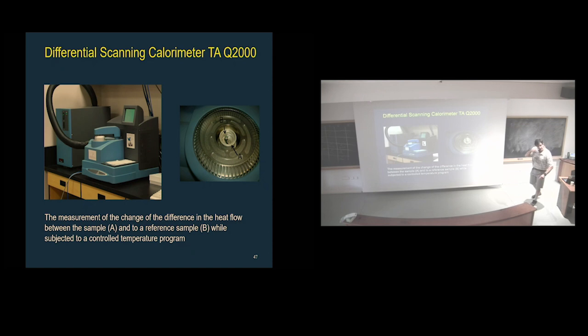So the DSC I told you about, I don't know if you're familiar with the machine. Very quickly, your sample, a reference. There's more fancy ways of doing it, but this is an oven. So you heat up the oven, and you measure the difference in temperature between one pan and the other one. Up we go, oh, phase transition, latent heat. The reference sample still goes up. The other one stays behind. That heat is going to the phase transition. And the delta T is related to a heat flow, m C delta T.